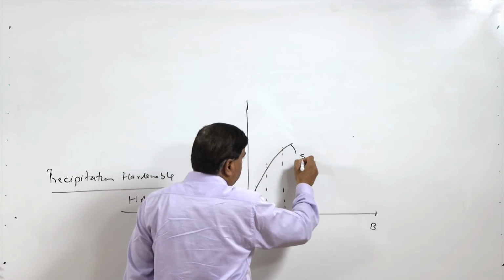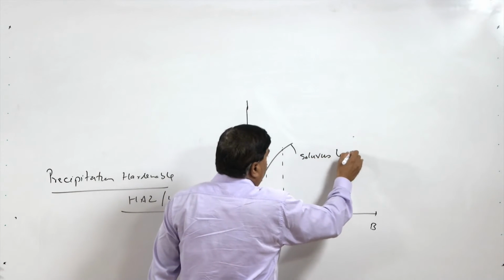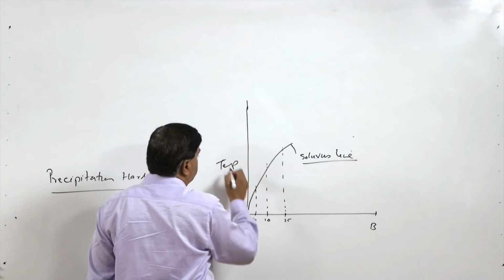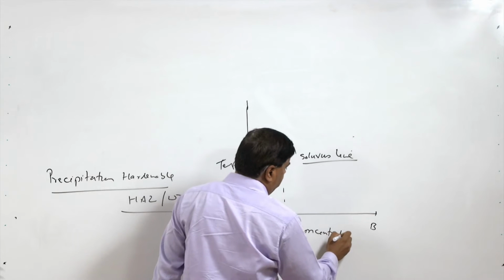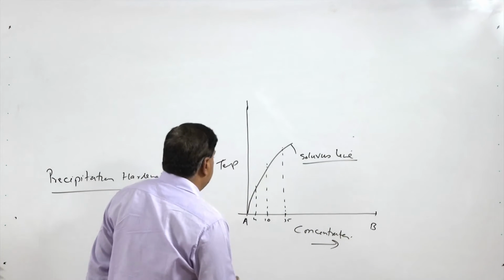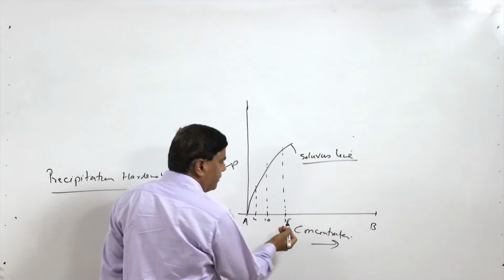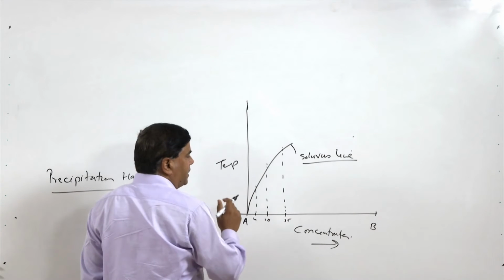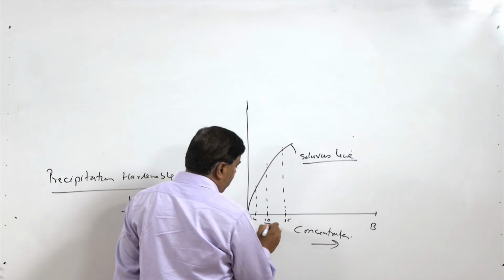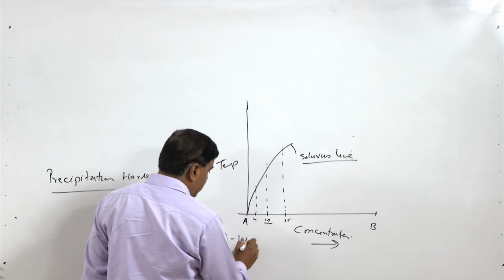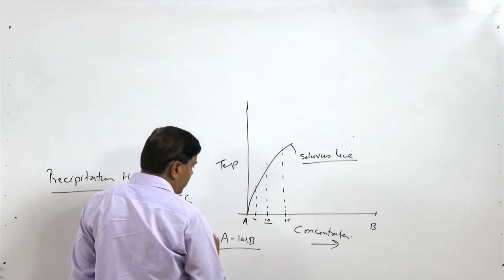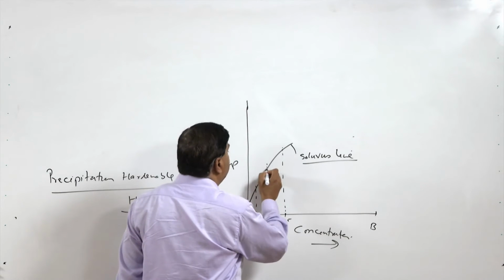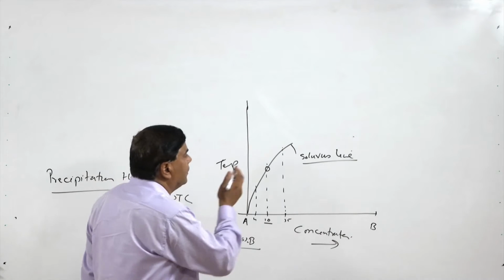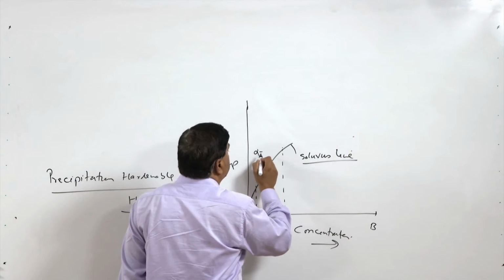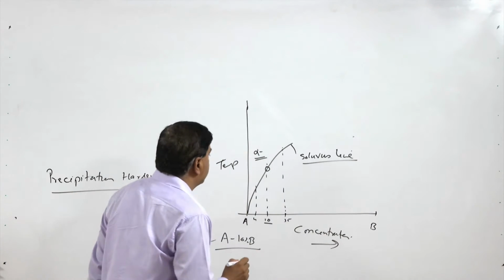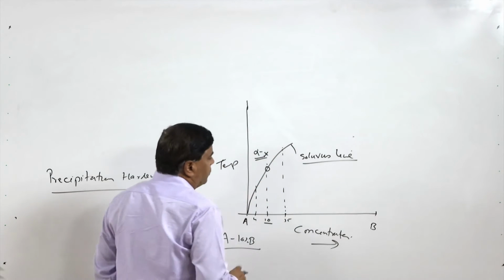So, the solvus line, or solvus curve, shows the relationship between the temperature and the concentration of the alloying element, and what it shows is that as there is an increase in temperature, the solubility of the alloying element in the matrix increases. So, what we do first, say for the alloy having matrix A with 10% of the B, this is an alloy just for example. Here this alloy will be heated above this temperature curve on the solvus line, so that we will have a homogeneous alpha system, a homogeneous solid solution is formed. So, we go well above this temperature to have the homogeneous solid solution.